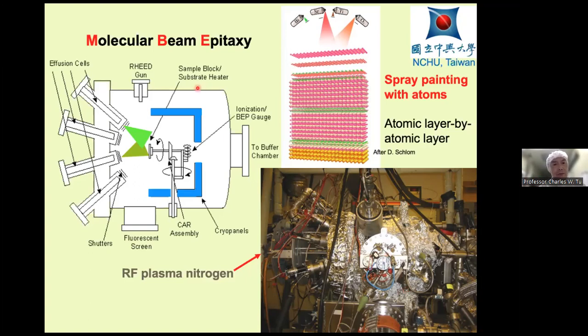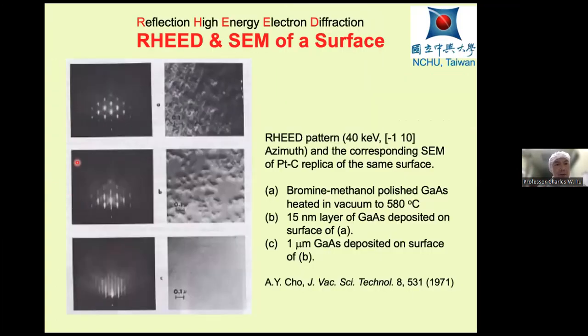Now, here I also want to mention we have an electron gun, which is almost parallel to the substrate surface, and here we have a fluorescent screen. The electron beam is at glancing incidence, about 1.5 to 2 degrees from the surface, so that it monitors the surface condition.